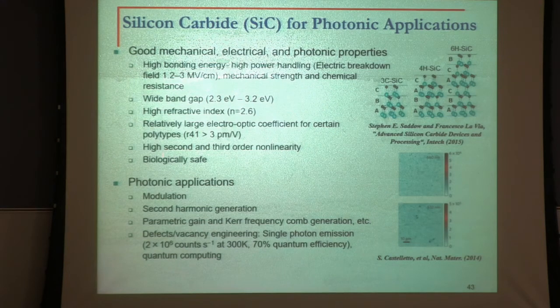It has very good second and third order nonlinearities. And by making carbon vacancies in it, you can make quantum dots. It's also a very good material at visible wavelengths, same as silicon nitride, of course less developed, but with a difference. Silicon nitride is an insulator, silicon carbide is a semiconductor. So you can still inject carriers and get faster modulation and tuning performance out of it. So there are lots of things. The reason we got into this is primarily the nonlinear and quantum aspects that silicon carbide can bring. Potentially it can generate single photon sources, single photon detectors. And that's the area that we are collaborating on with a couple of colleagues in Italy, who are experts in silicon carbide material.